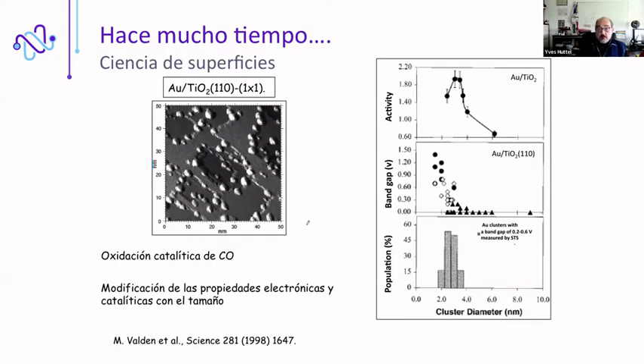So a long time ago, in the 80s, 90s, surface science was a fashion. And I want to show you this example because I like it pretty much. These authors deposited small clusters or nanoparticles of gold on top of a titanium oxide substrate. Here you have an STM image of the clusters. And they show that these clusters could oxidate the CO. And most interestingly, they have shown that the activity or the oxidation of the CO was pretty much dependent on the size of the nanoparticles or the clusters.